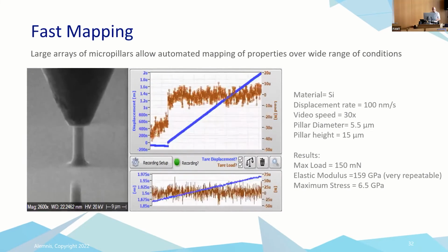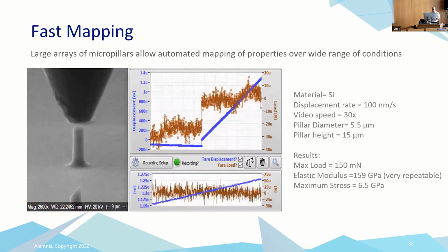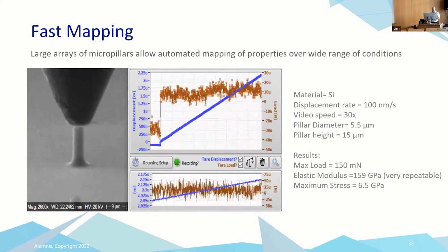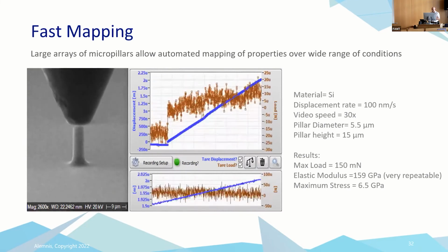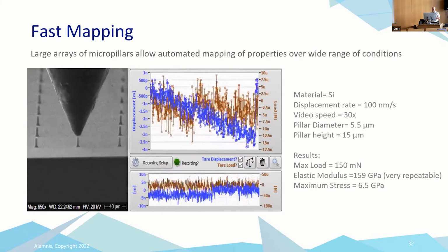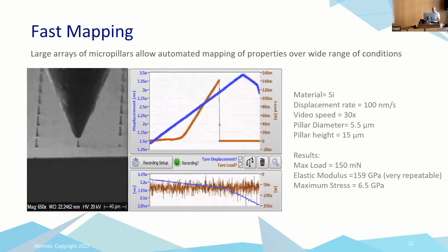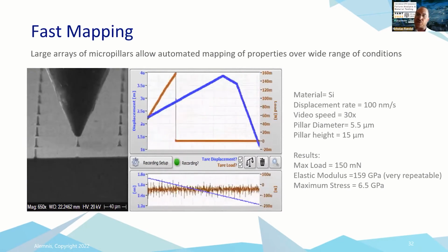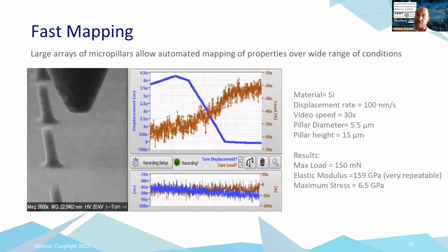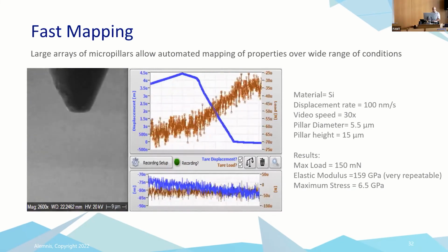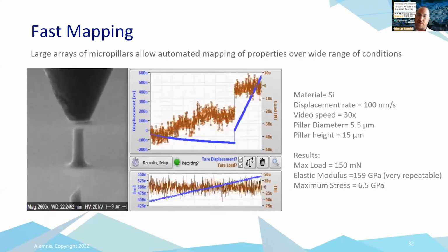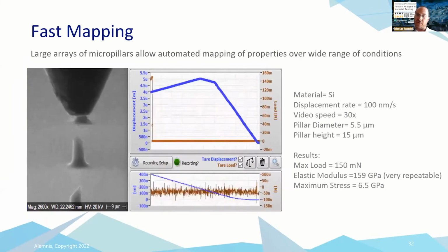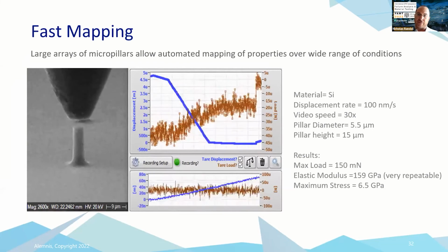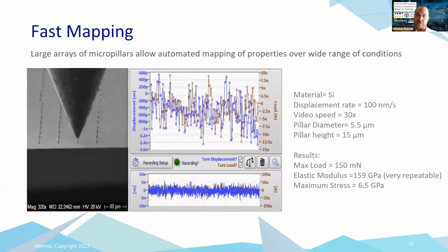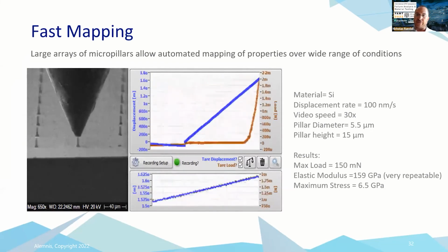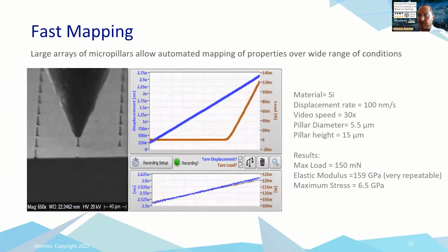Okay. And I have one other question. If I'm not mistaken, you said the displacement that you're doing in Z here is done by piezos. What is the range of displacement that you can have? So we have three ranges, 20, 40, and 100 microns. Okay. You've got to have a fairly big range, because if you're testing soft materials, then for a few millinewtons of load, you might be moving tens of microns, for example, in polymers. So you need to have a fairly wide displacement range.